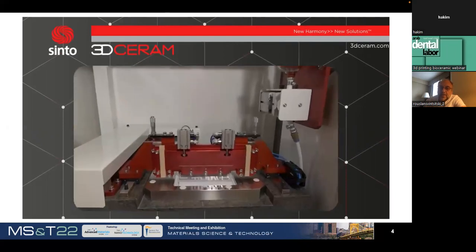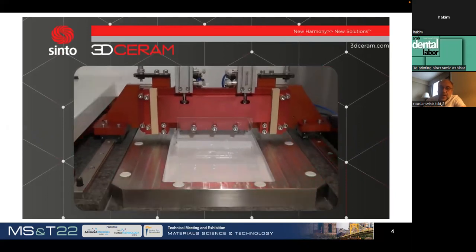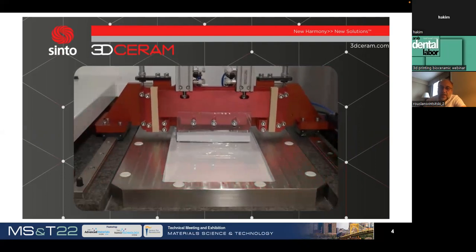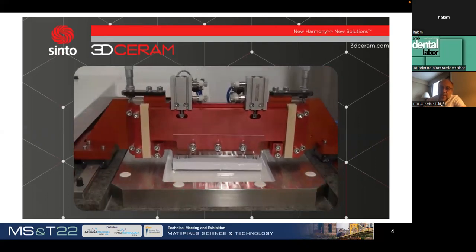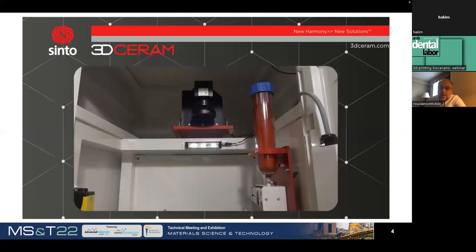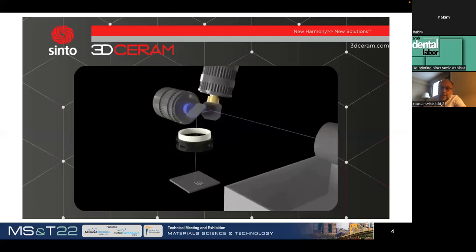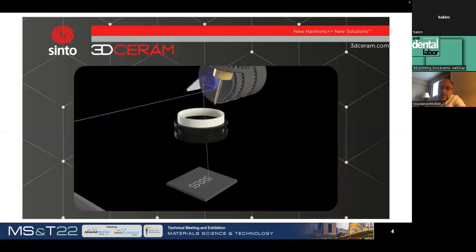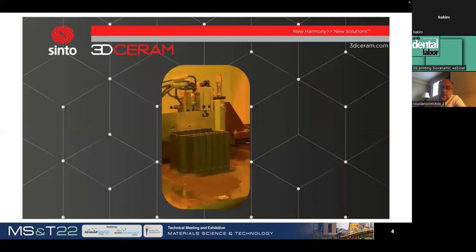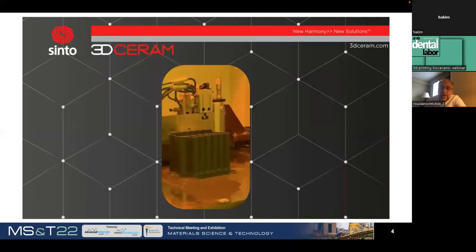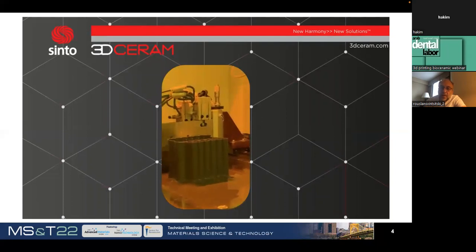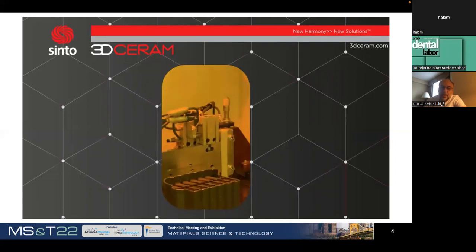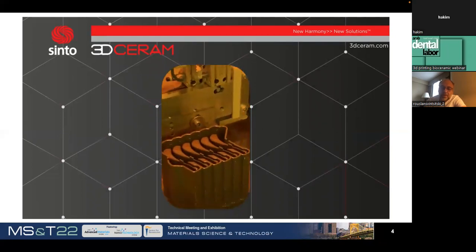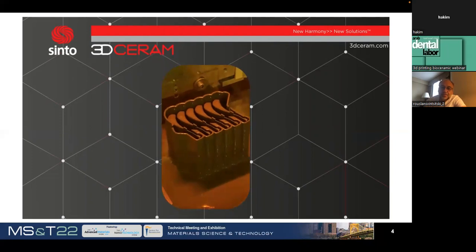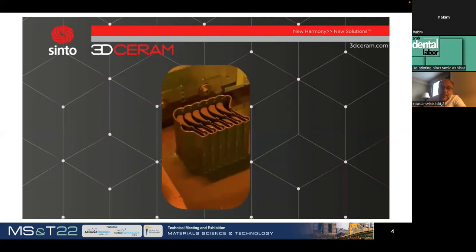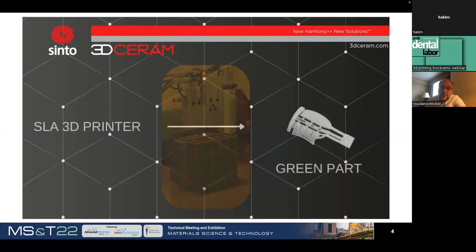Layer by layer, we dispatch this material, like you can see in the machine now, and to make it shaped or to make it hard, we use a UV laser of 405 nanometers of wavelength to cure each point all over the surface of the printing. And the parts are built layer by layer from the down to top. And then when the printing is finished, as you can see it here, the parts, the shaped parts are already printed and have to be post-processed.